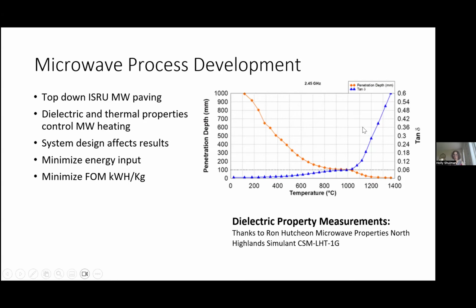So you can see that as you couple more, or suscept better, so you have better conditions for heating, it's intuitive that you don't have as much energy to go into higher depths. And that's really a good thing, because if you're putting microwaves 1 meter deep, you actually don't have enough energy in that whole volume to heat it very much. You're not at a temperature that's significant.